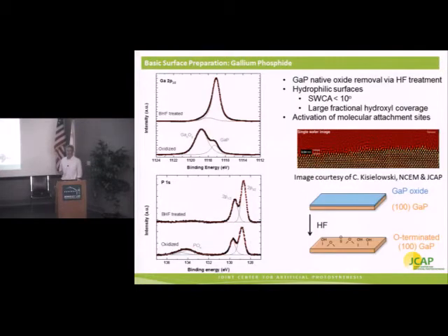In contrast, when we do the same treatment on gallium phosphide, we do not end up with hydrogen termination of the surface. Instead, we see that we are able to actually remove the native oxide. So we have a bare semiconductor surface, except it's then terminated by oxygen-bearing groups. And spectroscopic evidence points to a predominant coverage by hydroxyl groups.